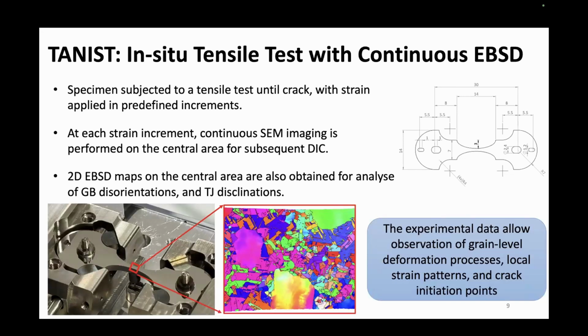digital image correlation. And the 2D EBSD is also taken at the central area. This here is an example, and this is the central area. This map can help us analyze the grain boundary disorientation, the changes in triple line disclination, and basically the variation in grains. And those experimental data will allow us to observe the grain-level deformation process, especially in relation to local strain patterns, grain boundary disorientation, and triple line disclination, and in relation to crack initiation points.